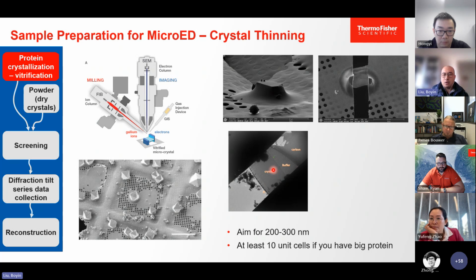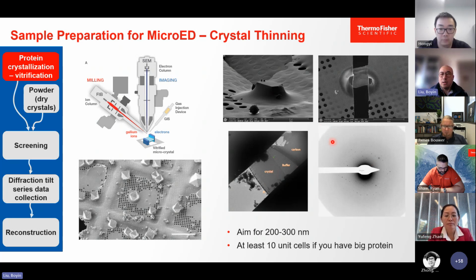You can diffract directly on the crystal, and you get very good, very sharp signals because the excessive buffer has been removed. For the thickness, we recommend 200 to 300 nanometers, because it's quite different from cryotomography. Cryotomography people really aim for thinner lamella because they think they get better contrast, especially for people trying to solve the protein with subtomogram averaging. They are trying to get down to 100, 150, or even 100 nanometer lamella. But this is not the case for MicroED.